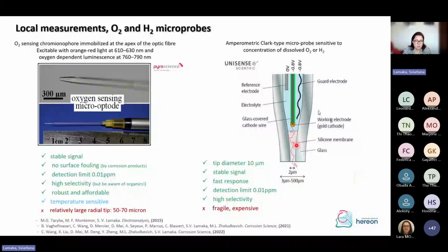Now, the unique feature of the equipment that we have is that we integrated all these commercial microprobes from Unisense, which is pH, oxygen, hydrogen, or from Pyroscience, which is microprobe. We integrated them into our SVET equipment so that we can correlate position of the probe with its readings. And this is very important because otherwise, neither Unisense nor Pyroscience, at least to my knowledge, provides any means to correlate probe position with its signal.